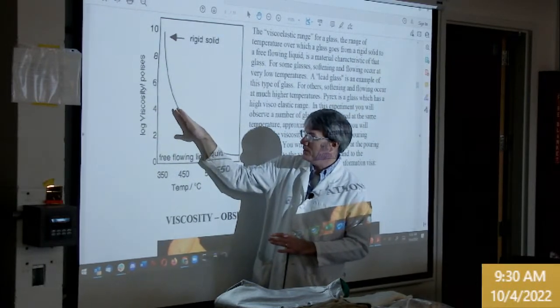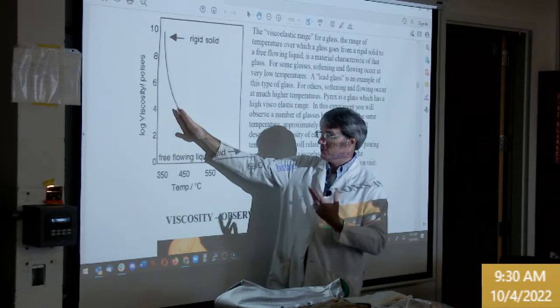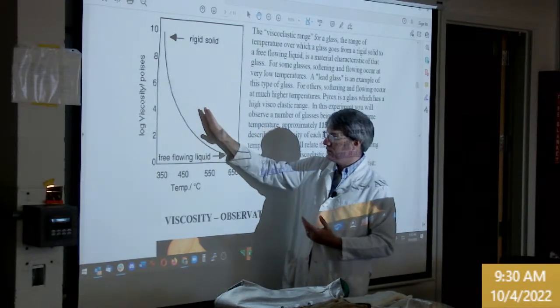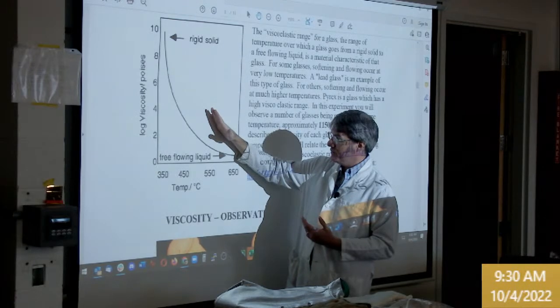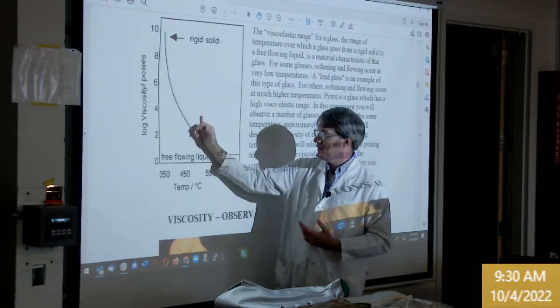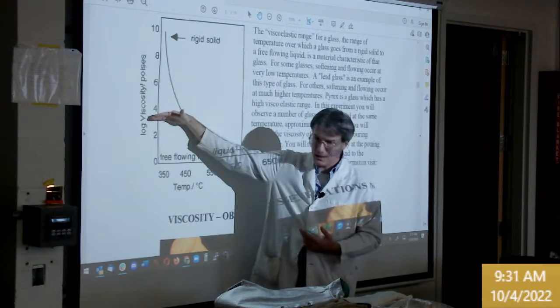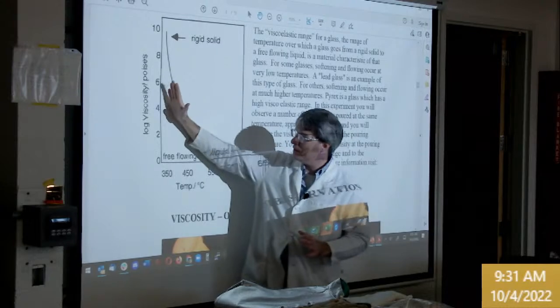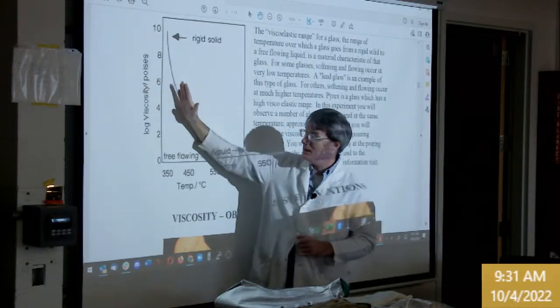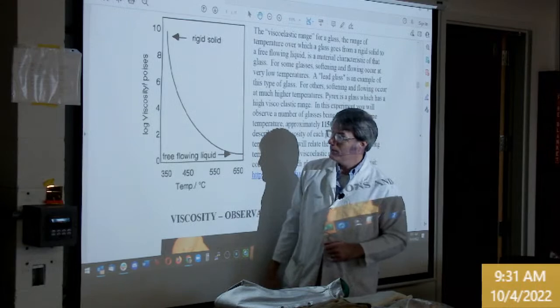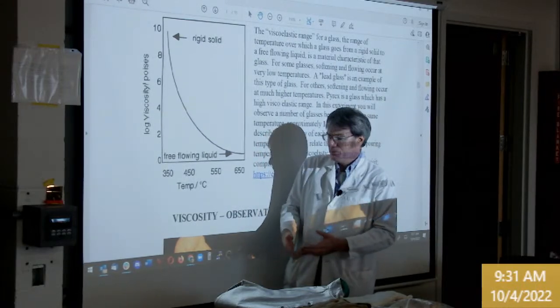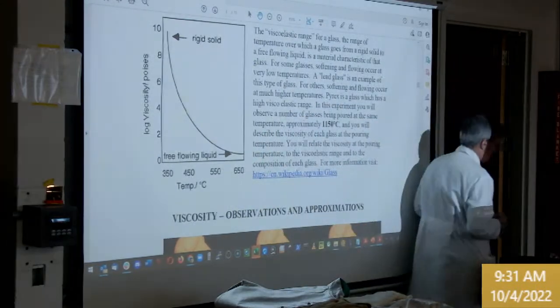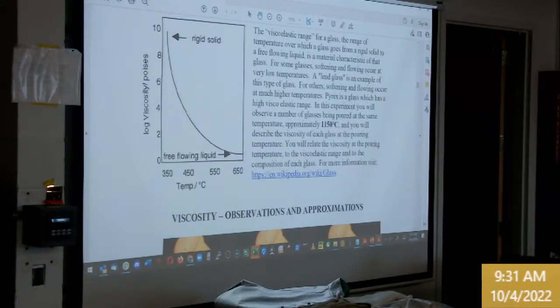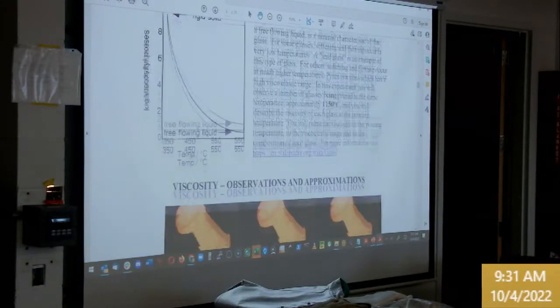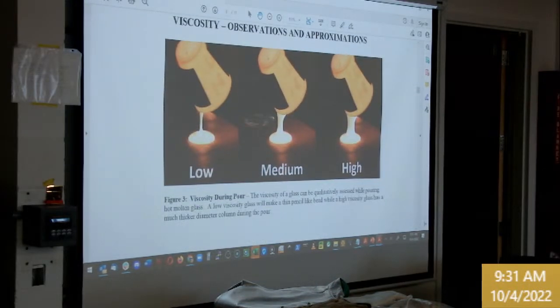If this was sodium, we would then add potassium as a replacement for sodium, and it would take this curve and shift it up this way, which would cause our viscosity to then be higher using that flux. Can you kind of see how that would work? We're shifting this curve based on the identity of the substance present. And that particular set is a pretty typical way of controlling that. And your viscosities during the pour would look different.